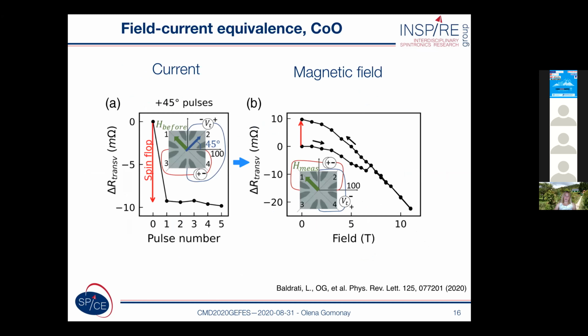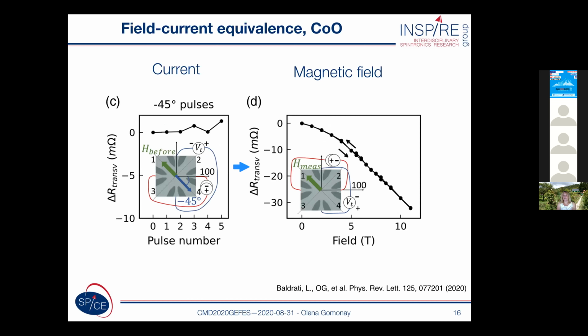So what experimentalists did, we first applied the magnetic field in order to orient the Néel vector in a certain direction, which we know, and then we applied a pulse of the current, and we knew the orientation of the current and the Néel vector for sure. So what we see for one orientation of the current, shown with a blue line in the figure, the system shows behavior which is consistent with spin flop behavior induced by the magnetic field. If we apply current in the other direction, 90-degree rotated, then nothing happens.